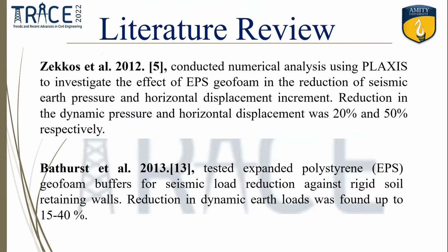In the literature review, Zekkos and others in 2012 conducted numerical analysis using Plaxis to investigate the effect of EPS geofoam in reduction of seismic earth pressure, and the dynamic earth pressure and horizontal displacement of the wall were reduced by up to 20% and 50% respectively. Bathurst and others performed the experiment against a rigid soil retaining wall, and they found a reduction in dynamic earth pressure of 15 to 40%.